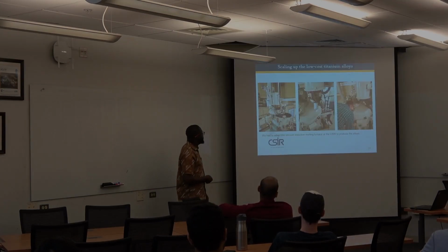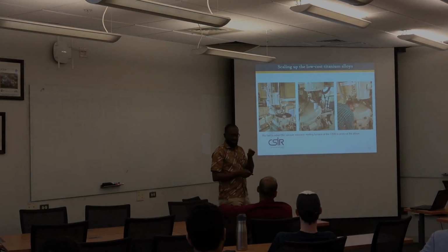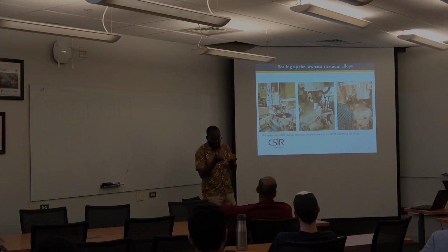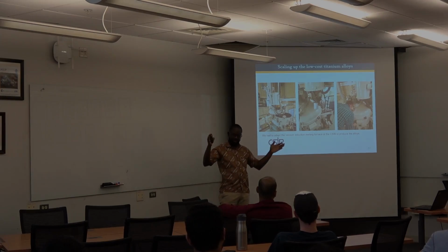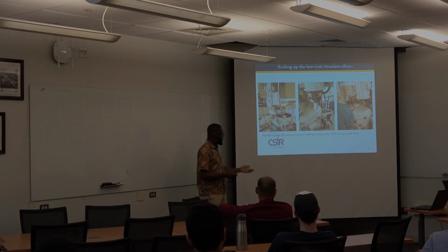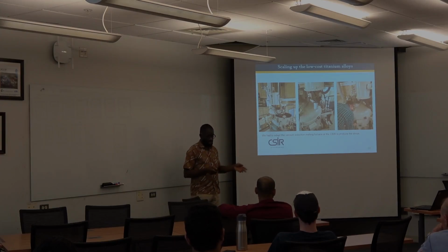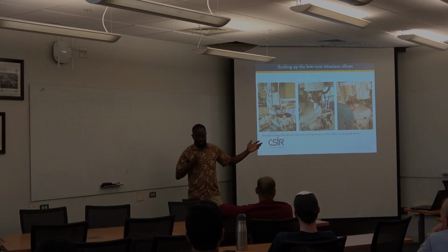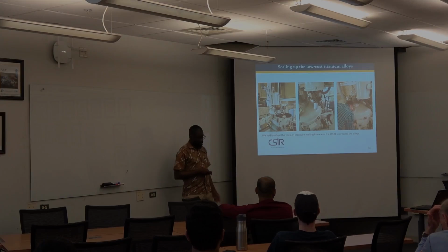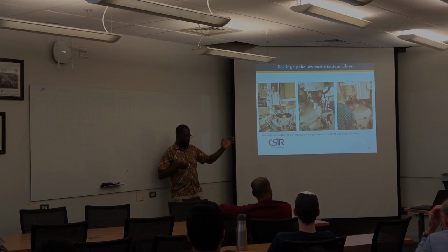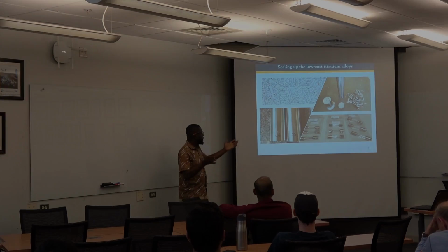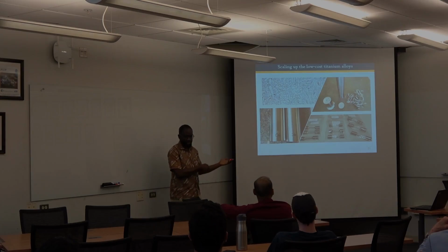Basically, so we thought, okay, just having 50 grams is not enough. At least when they patented the powder, when they were trying to make the powder, it was good at lab scale. They created a pilot plant and just slowly changed. So we tried to scale it up. We didn't have the right facility to do that. This particular furnace is used for producing single crystal nickel, basically at CSIR. So we had to adapt it in a way to produce a larger scale.